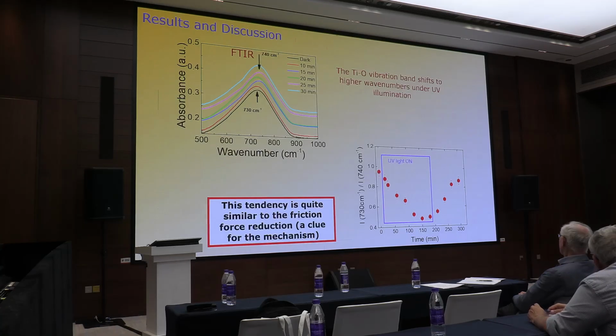I don't have the simulation here, but it's something like asymmetric versus symmetric vibration of oxygen bound to titanium on this surface. One is asymmetric and the other is symmetric. When it's symmetric, you can see a reduction of friction. This is the interpretation due to simulation. And also, we have an agreement with the infrared spectra. It's very important because we have an agreement between experimental results and simulations.